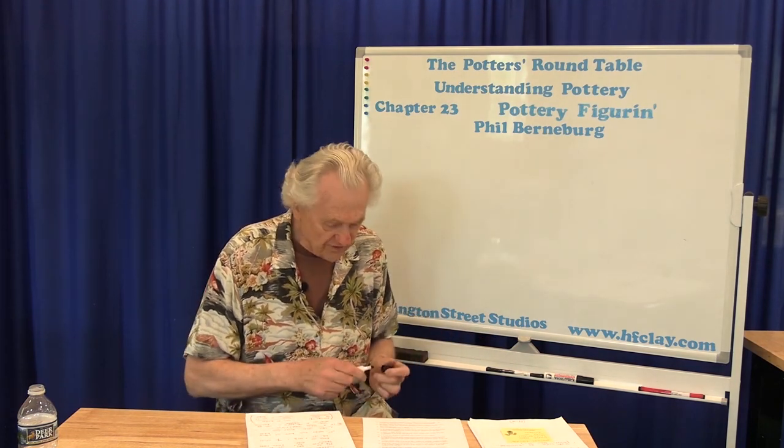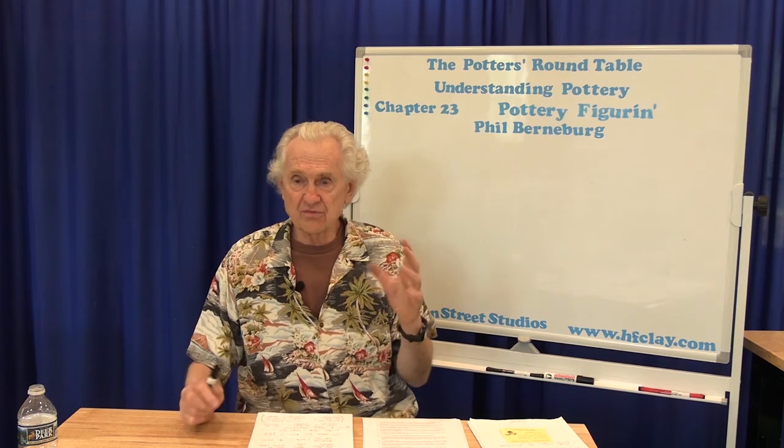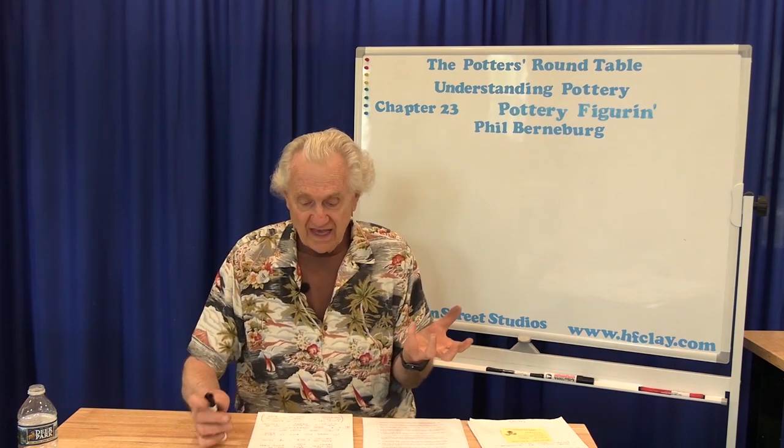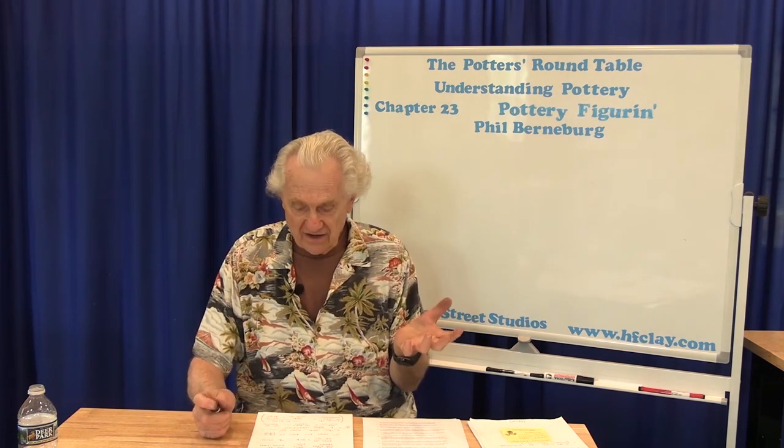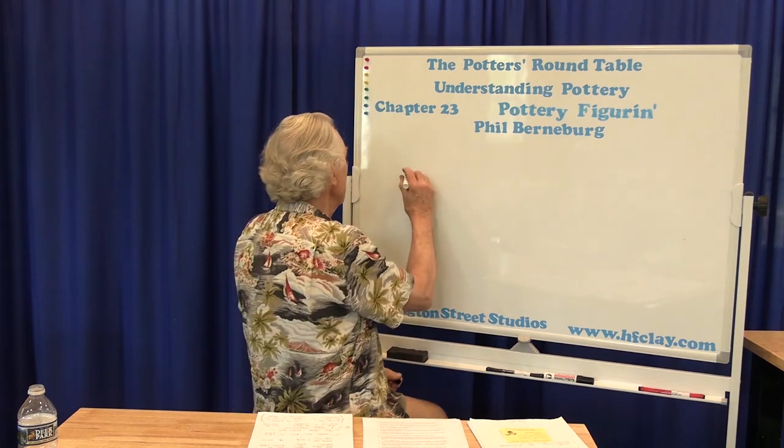So the first thing I need to do if I've got this bucket of glaze is determine how much water and how much solid powder I've got in it. The easy way to do that is to take a small sample of the liquid glaze and weigh it, and then dry it, let it sit around and dry, or put it in an oven, and then weigh the dried glaze.